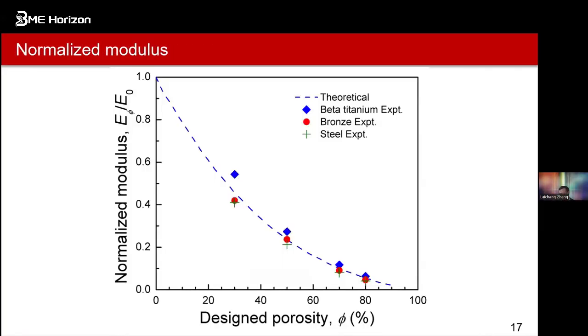Of course, based on these, we can see the structures we designed. We measured stiffness of different materials, from titanium, from bronze, from steel, relative to the range of porosities. We can also plot the structure's normalized modulus on the y-axis and the designed porosities on the x-axis. For normalized modulus, we take the Young's modulus of each structure at a given porosity and divide it by that of the 100% solid part. So that is the normalized modulus. Now, of course, we can see the density. So this is the curve.